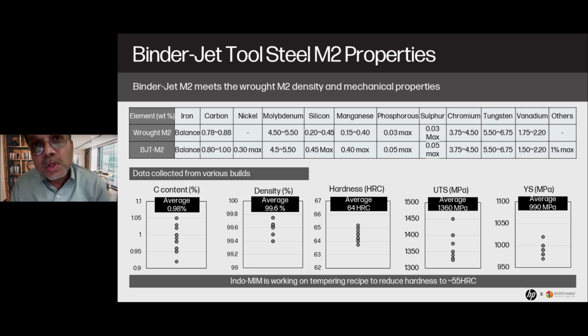So coming to how we are able to achieve these things. Of course, people have always used the wrought material, wrought M2, for producing the tool. What they are not able to achieve, binder jet material is able to achieve. Initially we were also a little surprised, but when you metallurgically analyze and compare the microstructure, it is very clear why a 3D printed binder jet tool element behaves that way and offers you 200 to 300% improvement in the mold life.